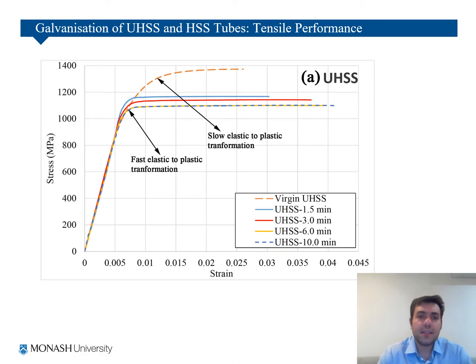Here you can see the stress strain curve of ultra high strength steel tubes before and after galvanizing for different galvanizing durations. As you can see, we have a reduction in yield strength, but it is not much. It can be tolerated. So even after galvanizing the ultra high strength steels, we can see that the transition from elastic to plastic is much faster, because galvanizing works like annealing, and it is working like a stress relieving of the cold forming of these types of tubes.